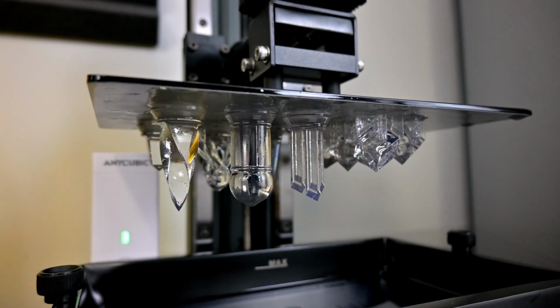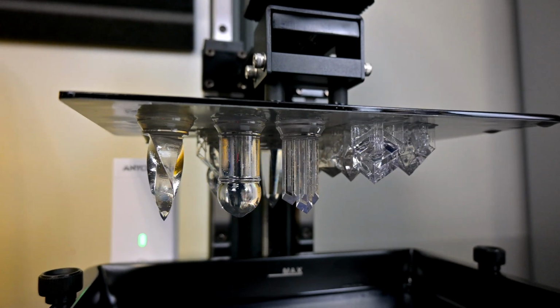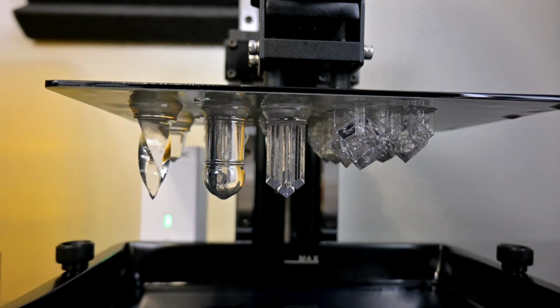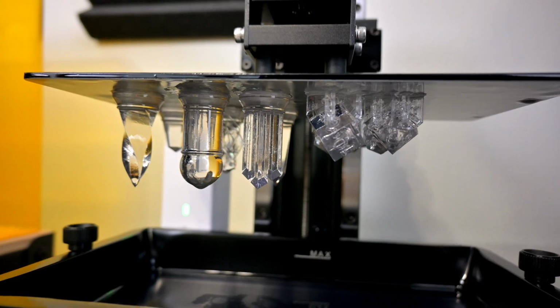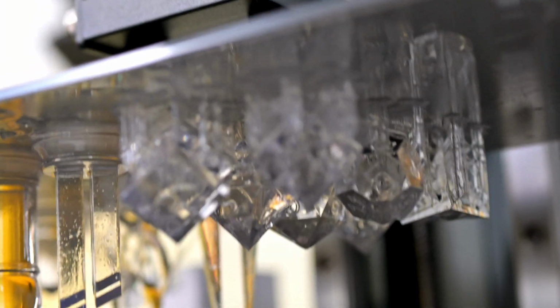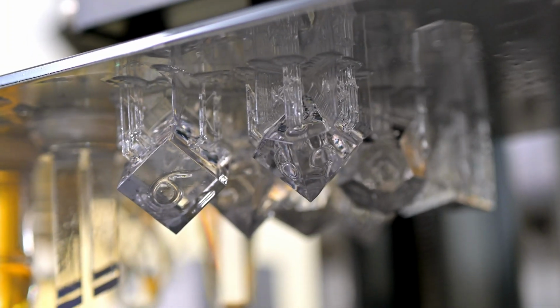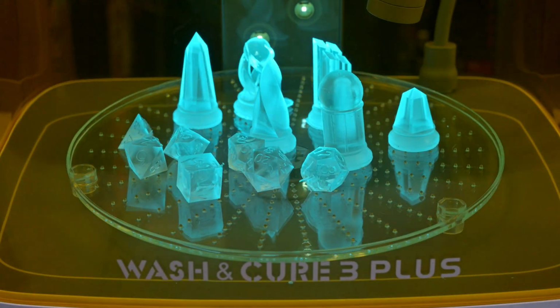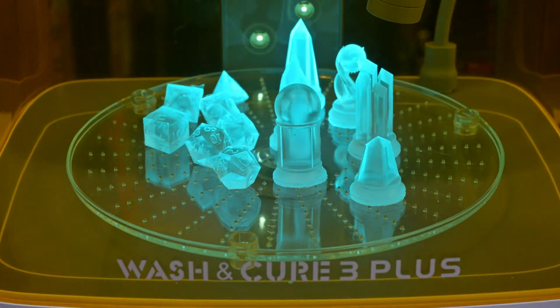And being a clear resin, I had to test 2 things. First, would it become see-through by polishing? And second, would a clear coat increase the clarity? So I printed some dice and chess pieces. And while still coated in resin out of the printer, they looked incredible. But as expected, after washing and curing, some of that transparency went away.